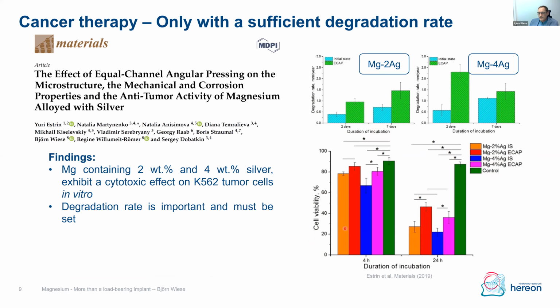If you look at the cell viability, so how many cells are living after 4 and 24 hours, when they are seeded on magnesium 2 silver as-extruded or ECAPed, or 4 silver, the same as-extruded or ECAPed material, we see that the quantity of the cancer cells gets reduced significantly after 24 hours and a bit already after just 4 hours of immersion. That means we can somehow treat the pure cancer cells in such an in vitro setup just by the corrosion. What at first glance was a surprise for me is that with a higher corrosion rate, I expected a higher death of cancer cells, but it's not true. So the corrosion rate must be adjusted somehow.